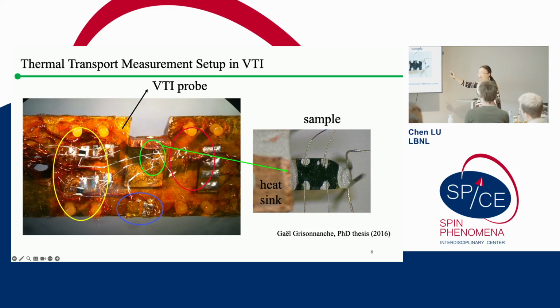So here I just use one of the cuprate materials, YBCO, as an example. So we'll put the sample on heat sink material and put it in the middle of the probe. And then surrounding the sample, you have all the other components like thermometers, heaters, which you can use to measure the thermal Hall signal directly.